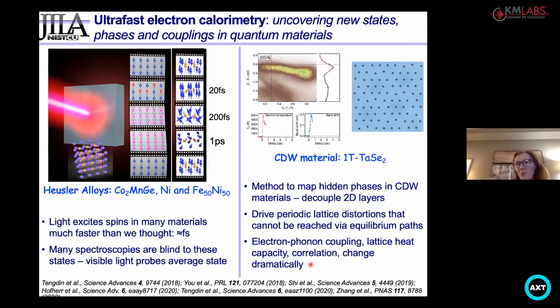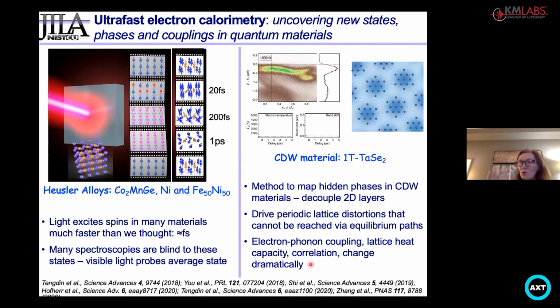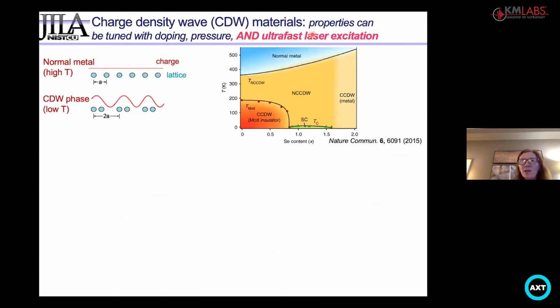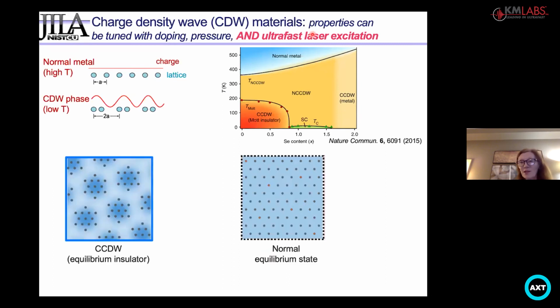the manipulating electron phonon couplings and driving lattice distortions that you just can't get to by dopant or strain. So they're quite interesting in opening up the phase diagram of these advanced materials. And so the example I'm going to give you is in charge density wave materials that are very interesting 2D materials. 2D materials in general are very important because we can tailor their electronic and photonic properties. And they're also very interesting from a physics point of view because charge density wave order is often close to the phase space of superconductivity.